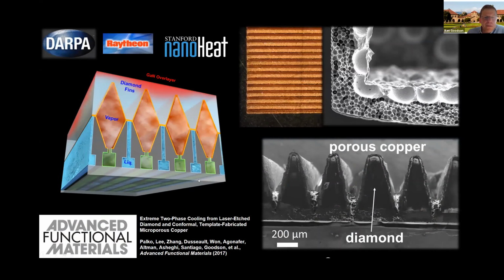So we made diamond fins, vapor phase, attached to a gallium nitride device, and then porous copper on the diamond. And this shows the porous copper. And here's a top view image, and you can see the device. And we published it in a couple different places. So what's happening with this